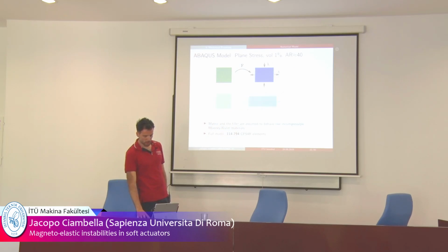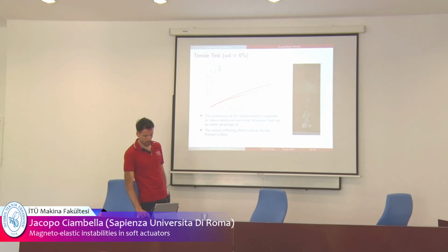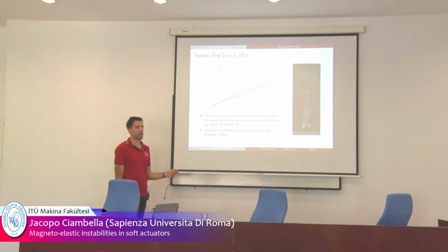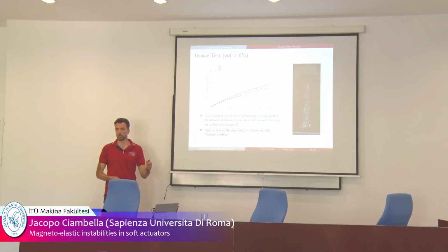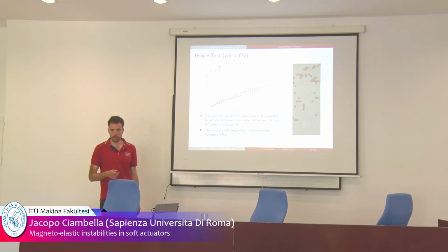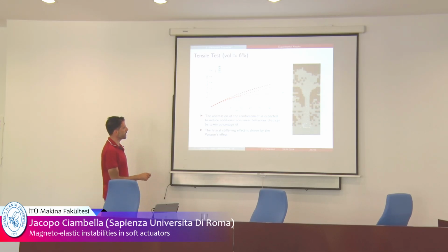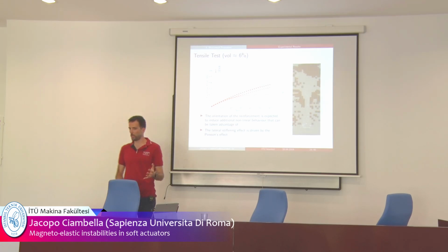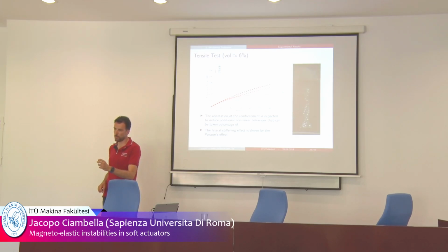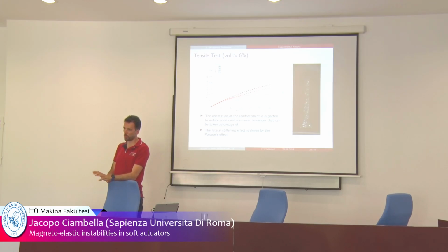Here, no, I skipped something. Here it is. So we did tensile tests, of course. We pull our specimen and we measure stress and strain. So standard quasi-static experiments. And these are the results. So this is an elastomer. We arrive at 60% of deformation, which is nothing for an elastomer. But for the experimental setup we had in mind, it is more than enough.